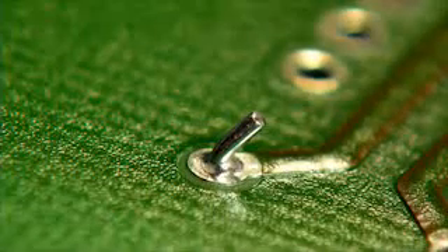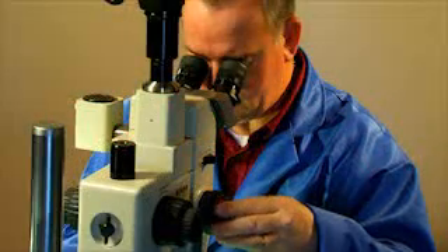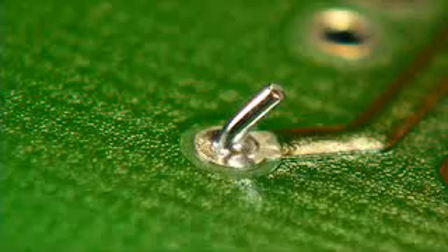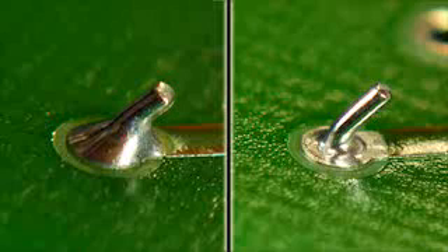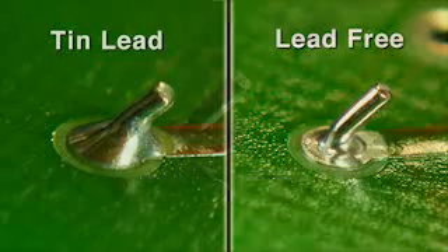Again, we clean the connection if required. The same inspection criteria will be used to determine a target solder joint. However, notice that the tin-silver-copper alloy is grainier in appearance than the tin-lead solder joint. This graininess is caused by the higher melting temperatures and is considered to be only a cosmetic issue.